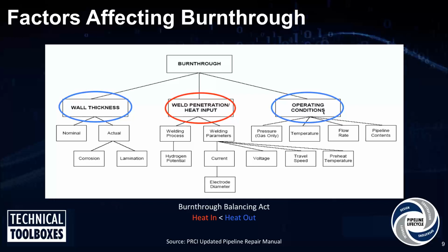From an engineering standpoint and from an in-service welding standpoint, we talk about welding heat input. What welding heat input is, it's a quantitative value that combines the arc voltage, the welding current, and the travel speed into a single value that gives an idea of how fast or how hot a welding arc is. So the higher the welding heat input, the more energy that welding arc is putting per a given length of weld.